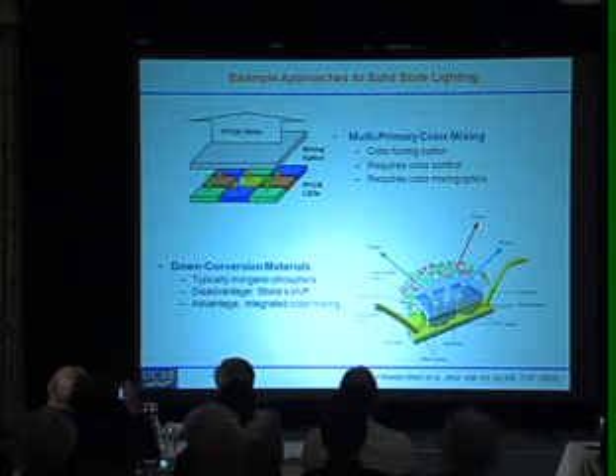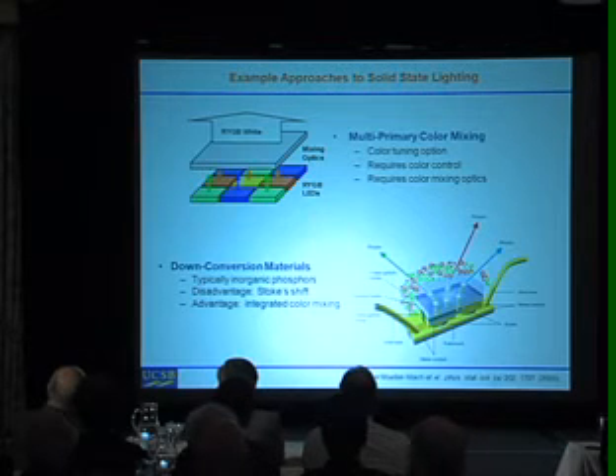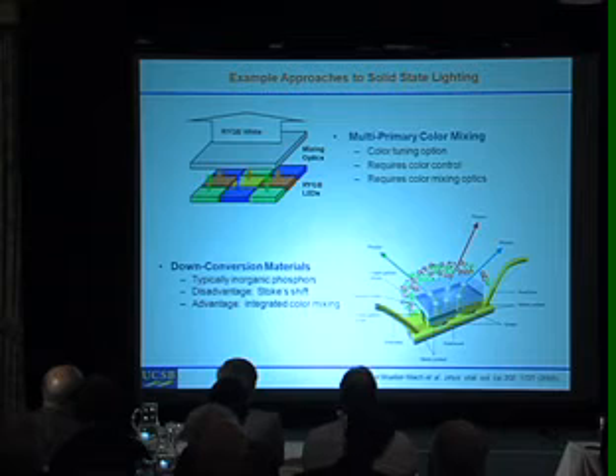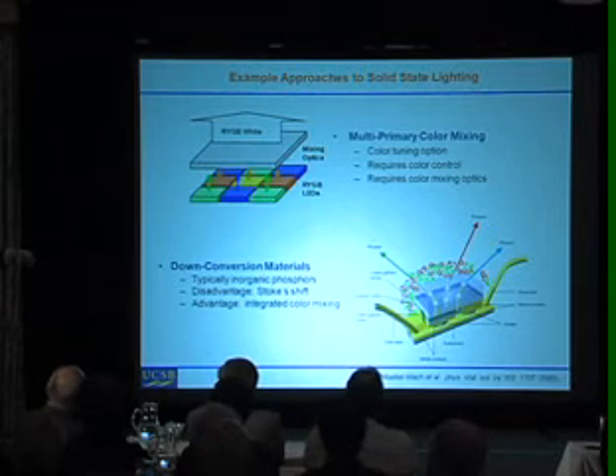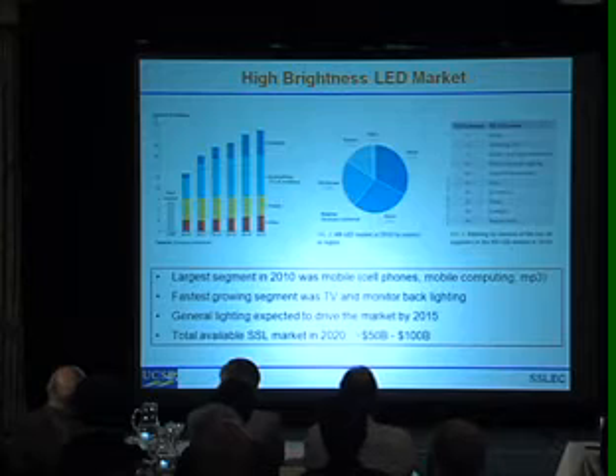Two main approaches for solid-state lighting is to take different color LEDs and mix these to make white light. This has not gotten very much traction in the field for two reasons. One, the green emitters are not sufficiently efficient now. The blue emitters are very efficient. And actually, the drive electronics for this still looks difficult, okay, to get good color mixing and combined with binning issues. Whereas the primary approach for making white light is to take a blue LED and combine it with a yellow phosphor or a yellow phosphor plus some other combinations of phosphors. And to the human eye, blue plus yellow looks white, okay? And this is the way that we do it, okay?